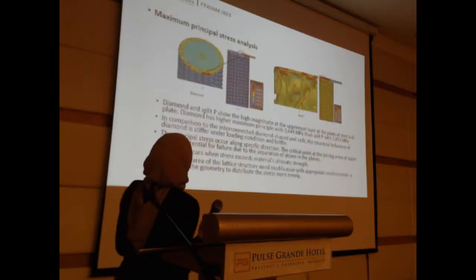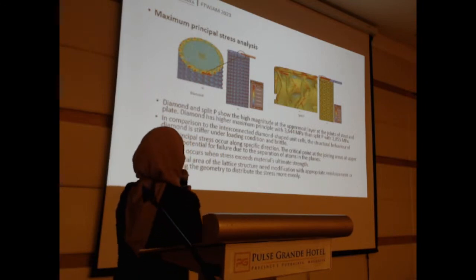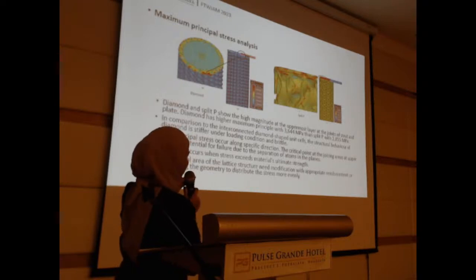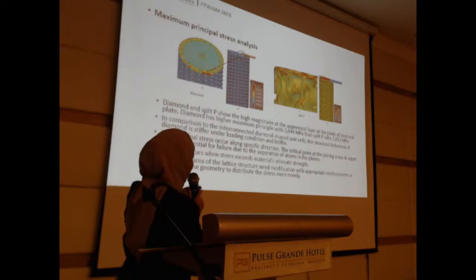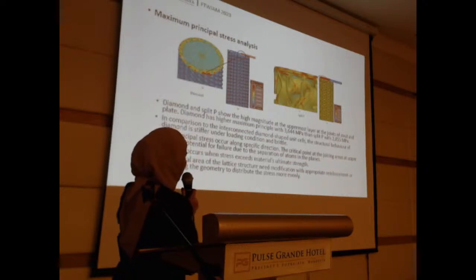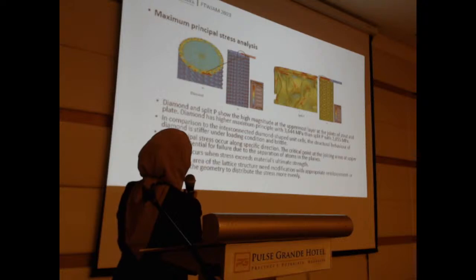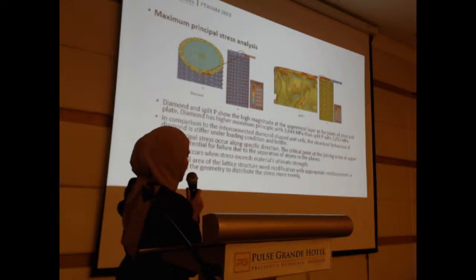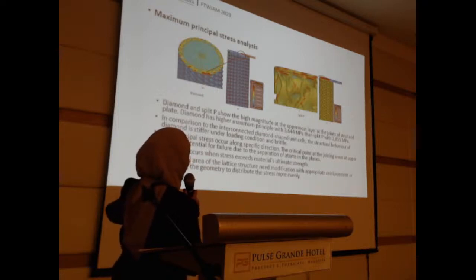Okay, maximum principal stress analysis. Diamond and split P show high magnitude at the uppermost layer at the joint of the strut and plate. However, diamond has a higher maximum principal stress, 3,645 MPa, compared to split P with 2,855 MPa. In comparison to the interconnected diamond-shaped unit cell, the structural behavior of the diamond is actually stiffer under loading condition, and it's brittle. The principal stresses occur along specific directions.